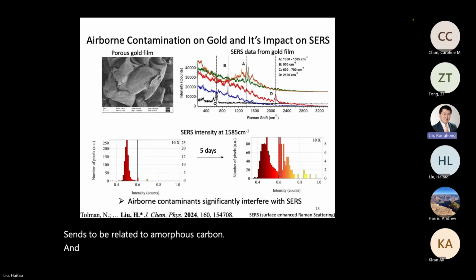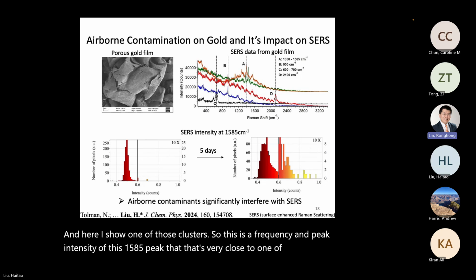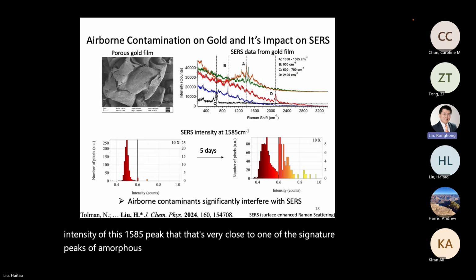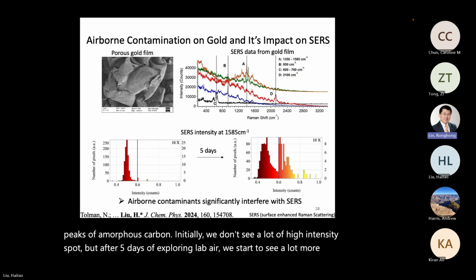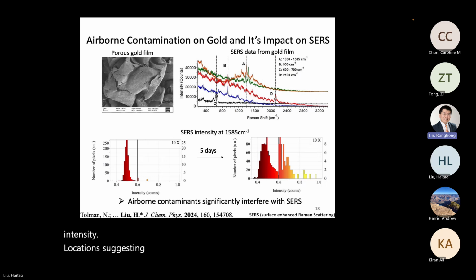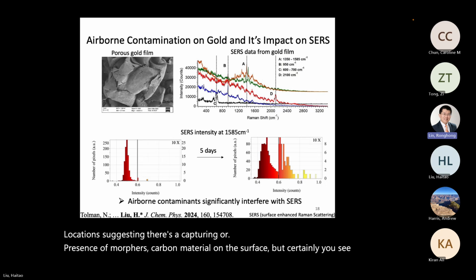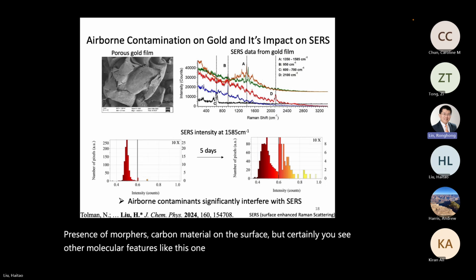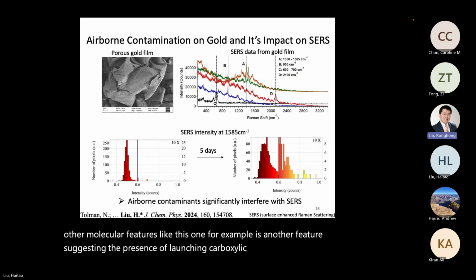And here I show one of those clusters. So this is a frequency and the peak intensity of this 1585 peak that's very close to one of the signature peaks of amorphous carbon. Initially, we don't see a lot of high intensity spots, but after 5 days of exposure in lab air, we start to see a lot more high intensity locations, suggesting there's a capturing or presence of amorphous carbon material on the surface. But certainly you see other molecular features like this one, for example, is another feature suggesting the presence of long chain carboxylic acid, and there are many other things going on.